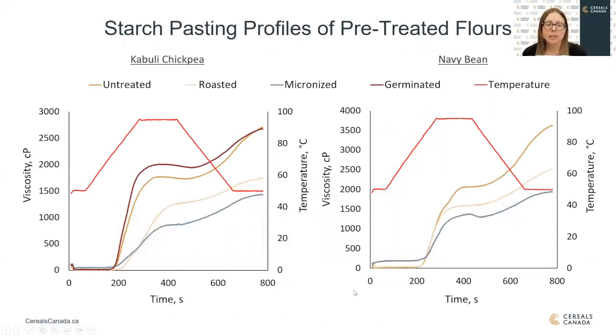These are the starch pasting profiles of the chickpea and navy bean flours. You can see that the roasted and micronized flours for both of these pulse types have a starch pasting profile that is quite different from the untreated. They have lower peak viscosities as well as lower final viscosities. And even the navy bean micronized flour has a little bit of a cold pasting viscosity at the beginning of its curve, which is likely due to the starch damage in that flour.